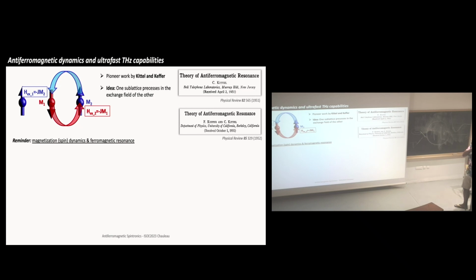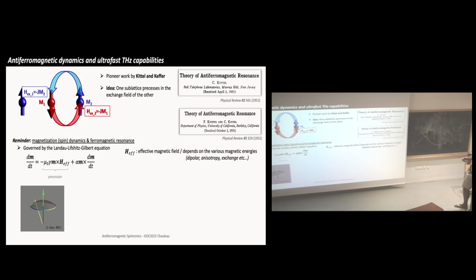But for this, let's do a quick reminder on magnetisation dynamics in general and ferromagnetic resonance. So typically, magnetisation dynamics is governed by what we call the Landau-Lifshitz-Gilbert equation. And this is this one. Basically, you have the time derivative of the magnetic moment, of the spin, whatever you want to call it, which is equal to two terms. The first term is a precession term. It's the equivalent of the Larmor precession. Basically, what's happening is that if you tilt the magnetisation away from its equilibrium, its effective field, then it will start precessing around it.